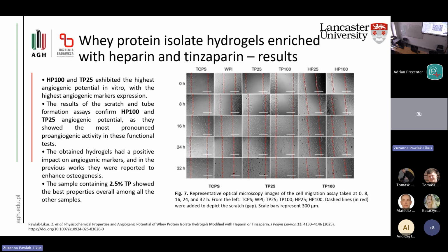after time, of course. The results of the scratch assay, and also the tube formation assay we made, confirmed that 100% of heparin and 2.5% of tinzaparin had the highest angiogenic potential, and those results were the same as results from relative gene expression, as the same samples exhibited the highest angiogenic potential in vitro because they had the highest angiogenic marker expressions. So our obtained hydrogels had a positive impact on angiogenic markers, and in previous work they were also reported to enhance osteogenesis.